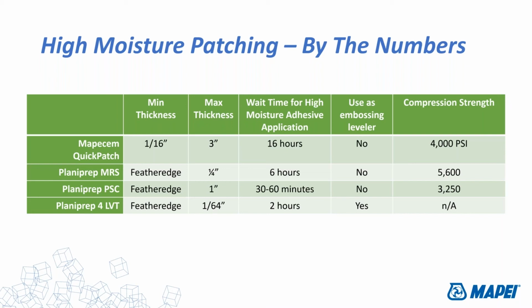Planiprep MRS is a feather edge to a quarter of an inch. We've got a little bit of a limit on that one. 6 hour dry time for moisture adhesive applications. I think MRS has a limit of 2 hours if you're putting a moisture controlling membrane on top of it, but 6 hours for glues. Can't use that for an embossing leveler, and a pretty high compression strength.